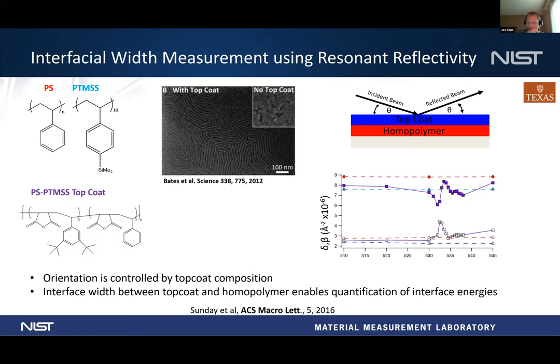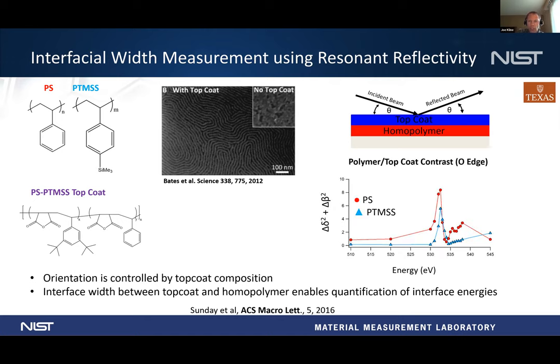And so now for the top coat material. In this particular case, we took homopolymers of the two blocks that you have there and then put the top coat on top of it. Grant Wilson's group developed a tunable top coat. They can adjust the chemistry of this top coat to change its surface energy, so that they can get the right surface energy for the top coat to get the block copolymers to stand up. And so we did the reflectivity measurements on these homopolymers.